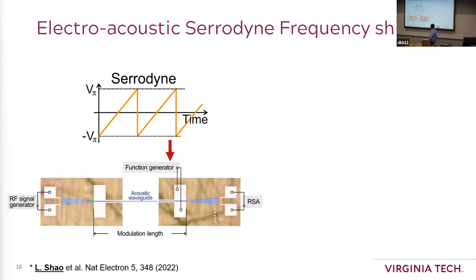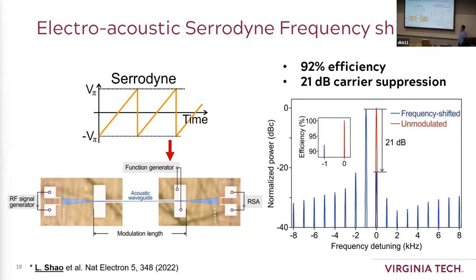The other thing is we can do frequency shifting. The way we do it is called serrodyne frequency shifting. If we apply a continuous phase change but always have a jump of 2 pi, your phase will change linearly over time, and the consequence is it will actually perform as a frequency shift of your original signal. By doing that, we can see that we achieve a frequency shift of the original signal to a 1 kilohertz offset with an efficiency over 90% and a carrier suppression ratio over 20 dB.